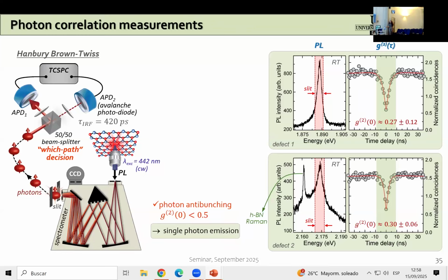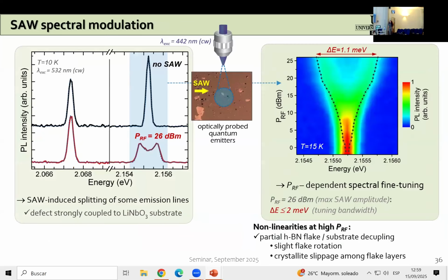So this means that these atomic defects in HBN layers are indeed emitting single photons. Now when we apply the acoustic wave to these atomic defects, what we see is that some of the lines also exhibit such apparent splitting, as you can see here. And this splitting also increases as we increase the acoustic power.